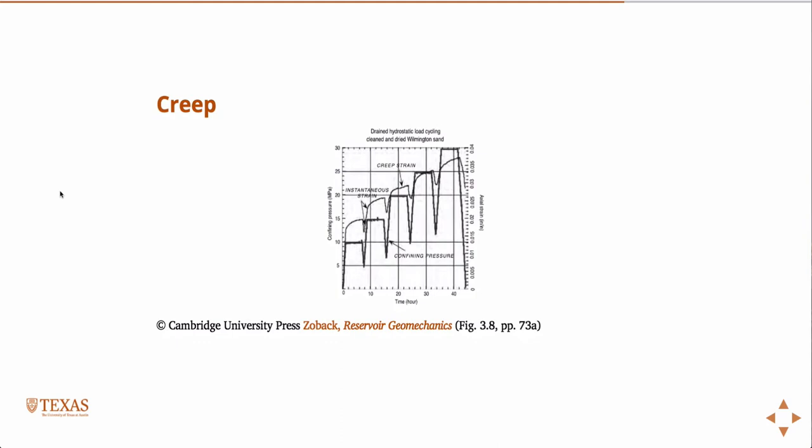Here's an example in the process of creep. This is some real data. What you see here on this line is the confining pressure. In this case, the pressure is ramped up and then held constant for so long. During that constant period, the strain is monitored and the strain continues to increase. This happens consistently for all time there. That's on a dried sand. That's an example of creep.